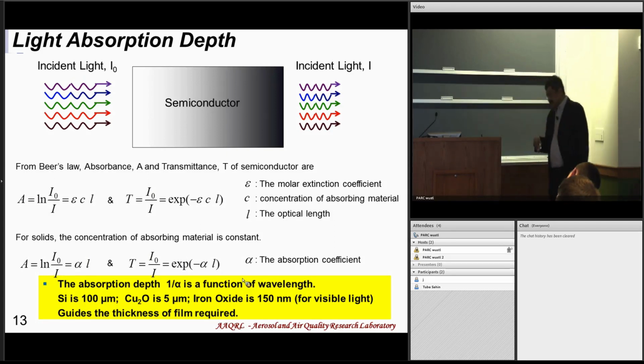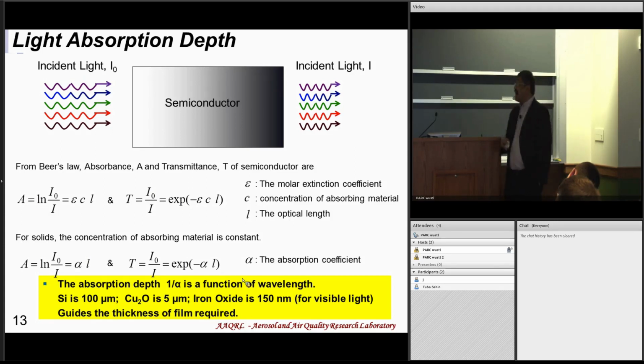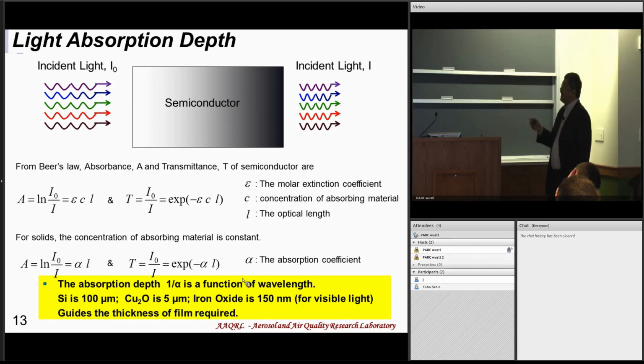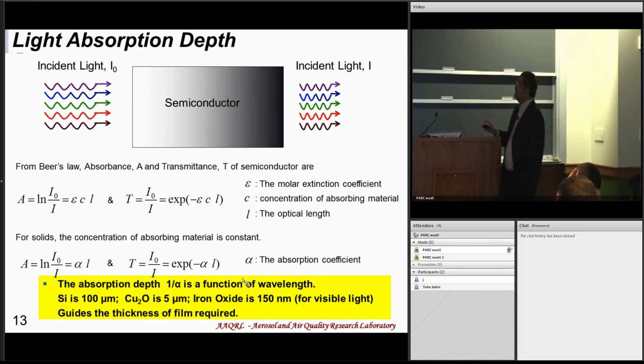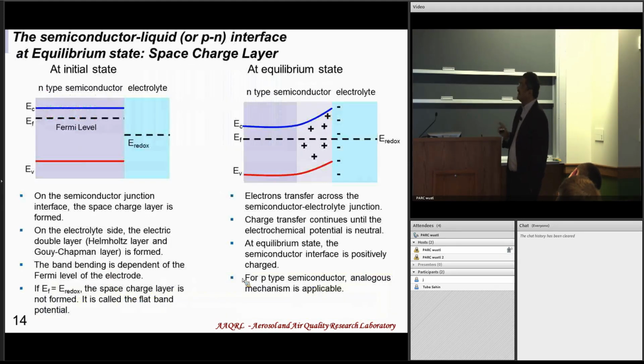The higher the absorption coefficient, the thinner the layer can be. So iron oxide is a good absorber in the visible ranges, so it could be relatively thin, and you can see that for a few other semiconducting materials. So that's another characteristic I keep in mind.